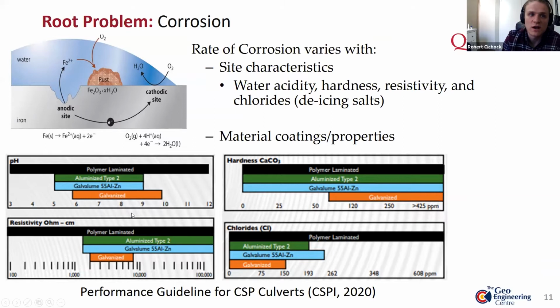So these charts are from the performance guideline for corrugated steel culverts, which is published in the technical bulletin by CSPI. As we can see, polymer coated laminated products have the best resistance to corrosion across all sorts of site characteristics. And this is mainly because the polymer acts as a barrier between the iron, which is a part of the structure material, and the corrosive environment, such as the polar solvent and oxygen. So it completely stops the reaction from being able to happen.